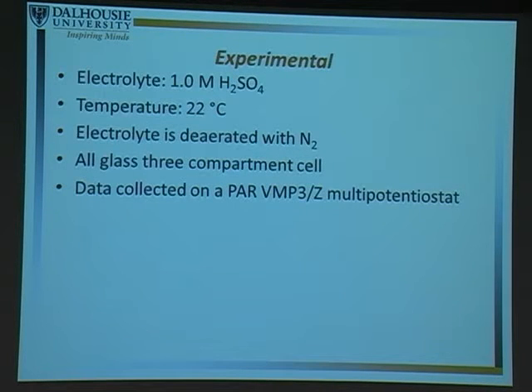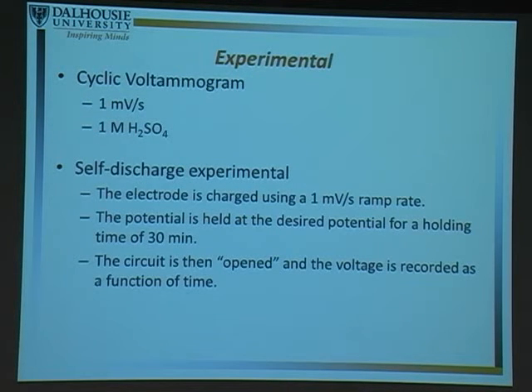So let's just quickly go through the experimental. These are the experimental conditions we use. We use one molar sulfuric acid. We use that because we have a high conductivity in these solutions. Room temperature, we deaerate with nitrogen. And the cell that we use is a three-compartment glass cell, which I'll show you a picture of.